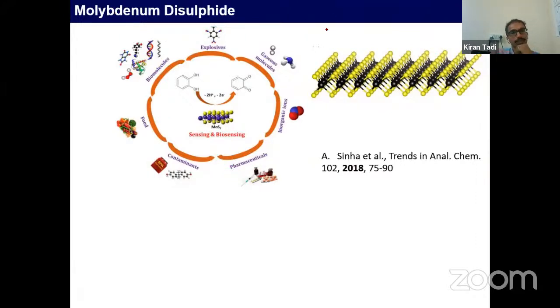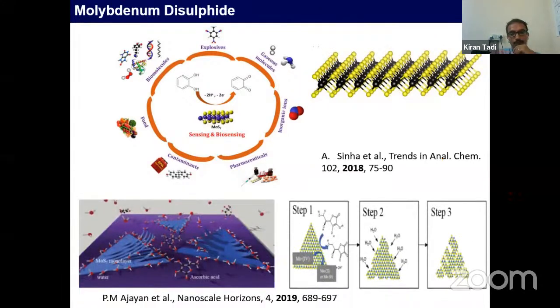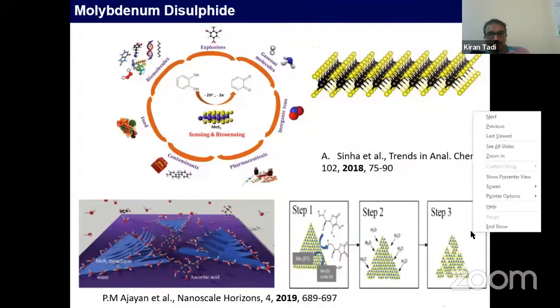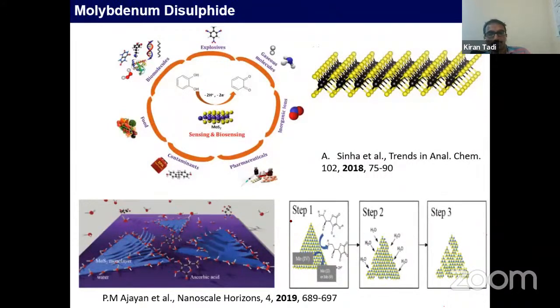We found a paper from P.M. Ajayan et al, published in Nanoscale Horizons, showing that molybdenum sulfide is not that stable when interacting with ascorbic acid and water molecules. It is slowly etching the surface of the molybdenum sulfide in the presence of ascorbic acid, which is a mild reducing agent, converting the molybdenum to some other oxidation level.